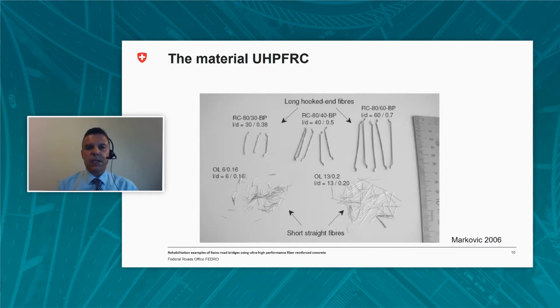Fiber content is usually expressed in terms of fiber volume fraction, representing the ratio between the fiber volume and the material volume, the latter being the matrix with the fibers. Fiber quantity varies in different types of this material, usually in the range of 1.5 to 2.5%, and in certain cases, for specific applications, it can reach up to 6%.